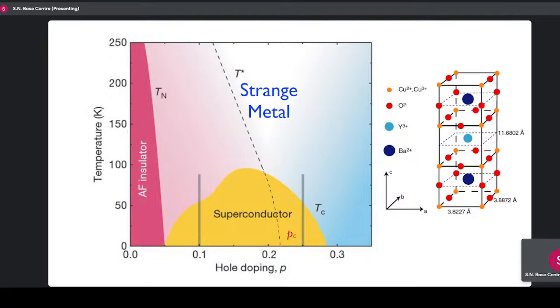On the other hand, if you take the cuprates and heat them up, you get what's called a strange metal, mainly because its properties don't agree with Fermi liquid theory at all. If you took a conventional superconductor like aluminum or lead, this would be a Fermi liquid. But in essentially all of the new correlated electron superconductors, including the pnictides and now recently the nickelates, all show this kind of strange metal regime.